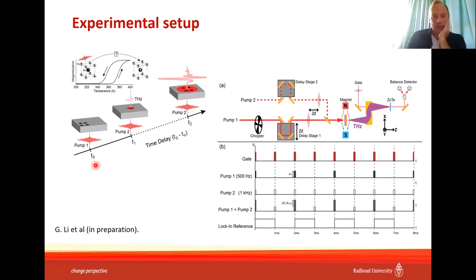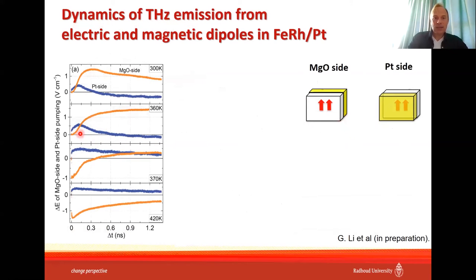Okay, so this was our trick. And in this case, we don't measure terahertz emission as such. We measure the ability of the nuclei generated by pump one to emit terahertz radiation. So we measure the terahertz emissivity of the nuclei generated by pump one. And this is the dynamics which we observed. You see that emissivity varies very slowly. Emissivity changes as a function of temperature,